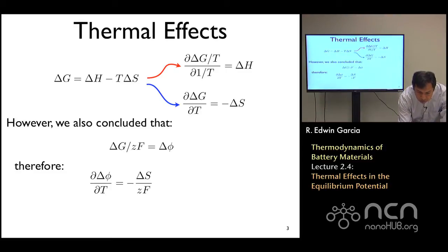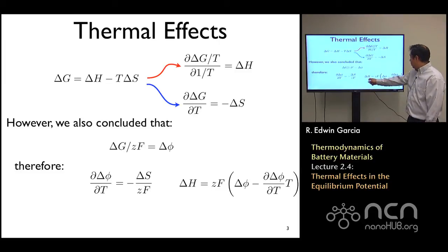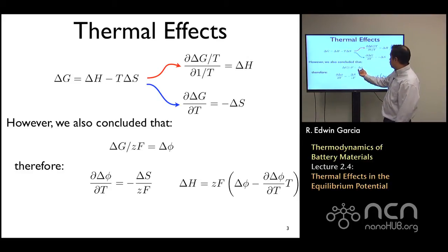Now, we also know that because the enthalpy is related to the voltage in this other way, we could use our measurement of voltage as a function of temperature to measure essentially the enthalpy of the system, as you can see here. It's very straightforward to do that—basically, just go and substitute this number over there.